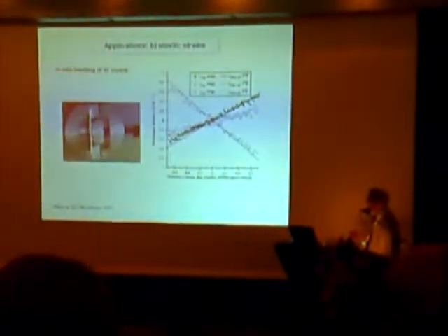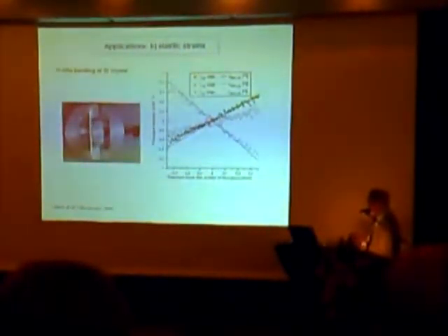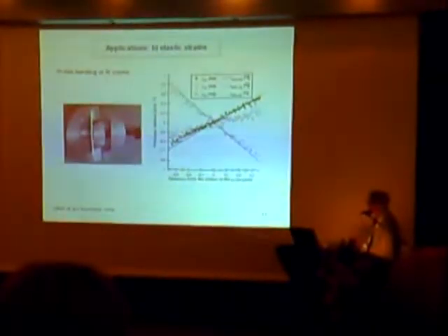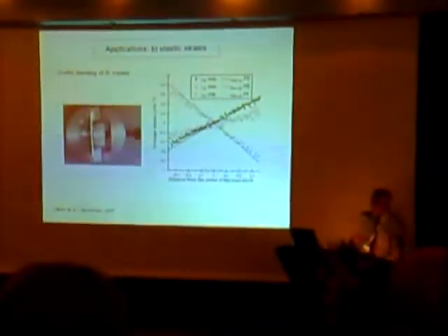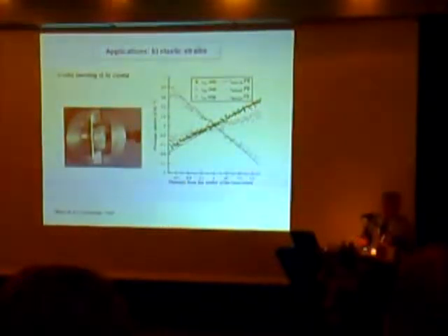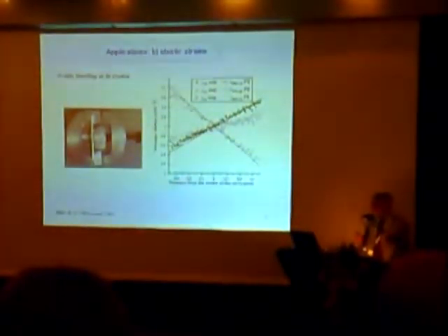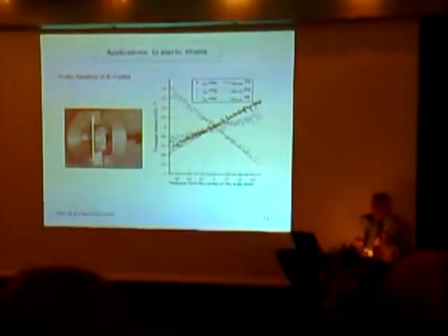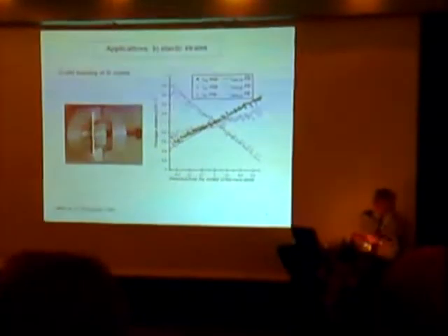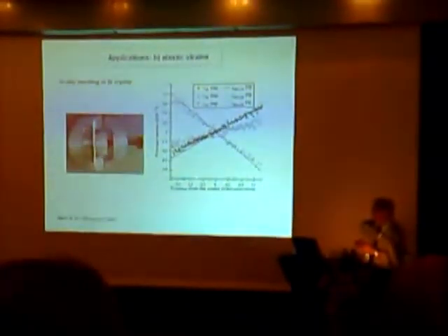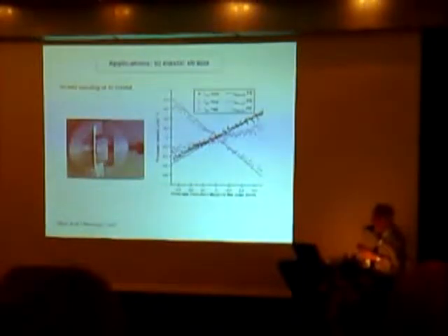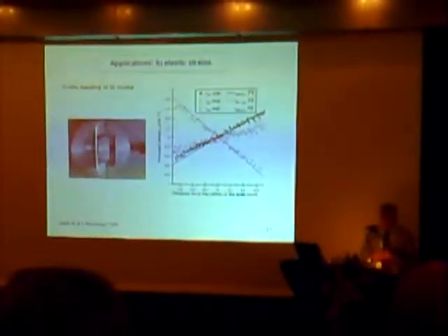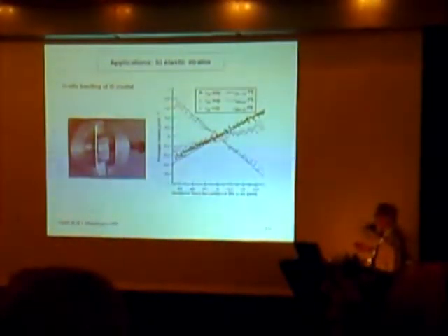So these are the strain measurements. Of course, the center should be 0, which it was. And since it's a simple beam, a bit anisotropic, you can calculate the exact solution. You know what they are? The exact solutions, in fact, are the straight lines for these different strain components. You can see that it's getting very good agreement.